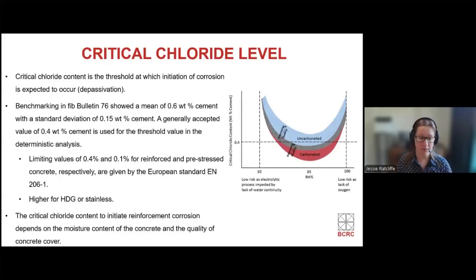Our critical chloride level is the amount of chloride at that reinforcing bar that we consider to be when it's likely to start corroding. It's typically taken as 0.4%, but different reviews and studies show, including the benchmarking FIB Bulletin 76, that is a fairly wide range. So it depends on your reinforcement, it depends on your structure, but the 0.4 weight percent is what we'll be using today.